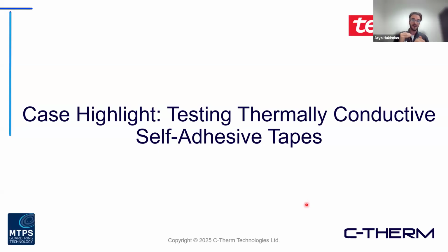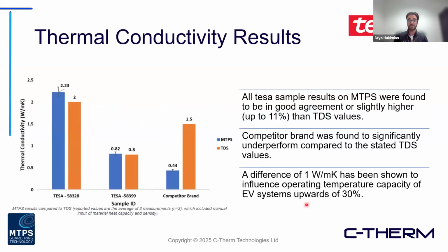They were seeing some very high heat being generated with some of the competitor brands, although the technical data sheet says the thermal conductivity was such that it should be dissipating more. So they came to us as a third party to validate some of these claims. We had tested two of their materials and found some pretty good agreement, actually even a little bit higher than what they were speccing using MTPS here. But overall, it made sense from that side.